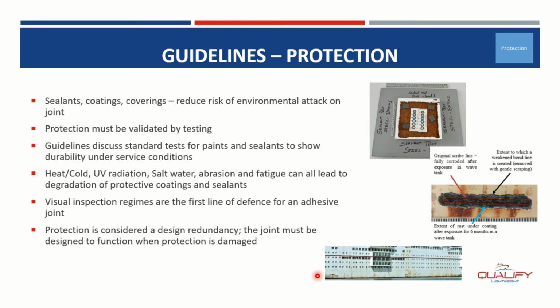We'd all like to think that we put our coating on, it lasts forever, but we know it doesn't. The same goes for sealant. It's important to understand if you're going to use a sealant to cover the joint and stop moisture ingress, that you assess that. There's standards out there to do that, or it can be as simple as just doing a test where you put some colour changing beads under a sealed panel and immerse it in fluid and see if that fluid then could be seen to change the colours inside the test sample. It's quite handy because you can see where leaks might be, etc. And it's a good way of just understanding the efficacy of a sealant so that you can use it for mitigation.